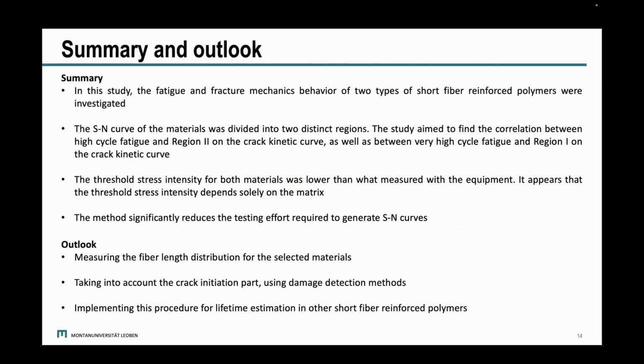So, summary and conclusion. In this study, we used two different short fiber reinforced materials and tried to derive the SN curve based on the fracture mechanic tests and based on the crack kinetic data. For the very high cycle fatigue regime, the method worked better than for the high cycle fatigue regime. And also, it seems that the threshold stress intensity depends just on the matrix, not on the fiber orientation and also not on the fiber content.